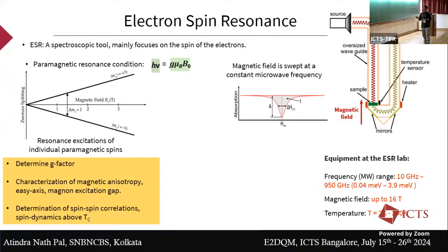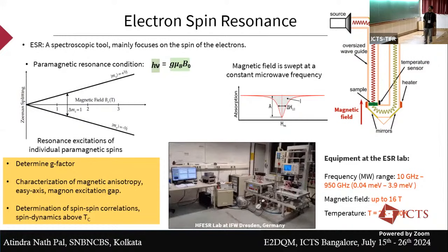Also, you can determine the spin-spin correlation and spin dynamics above TC, to see whether a short range correlation is present in this system or not. This Dresden lab has a frequency range of 10 gigahertz to 950 gigahertz, a magnetic field up to 16 Tesla, and a temperature range of 2 Kelvin to 300 Kelvin. And this is the experimental setup of the lab.